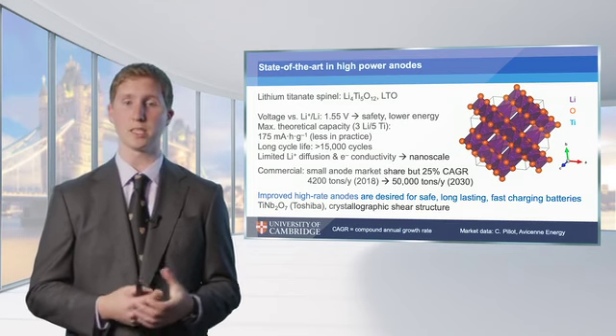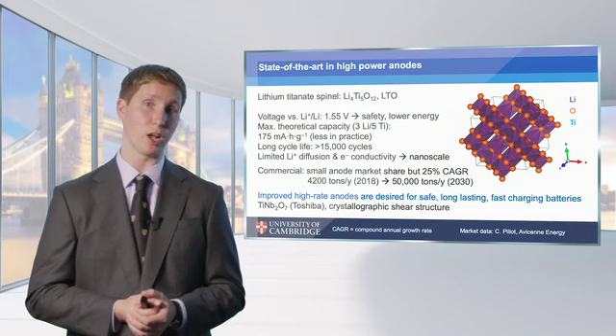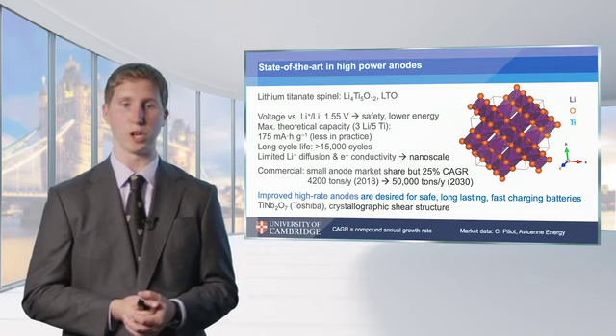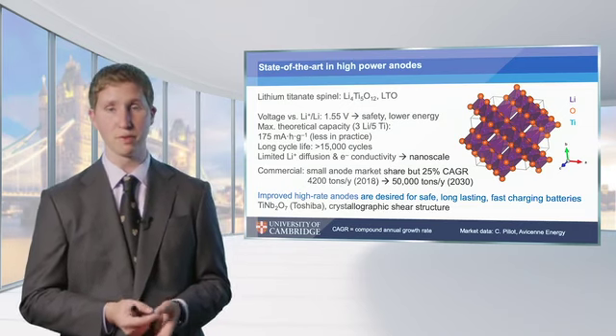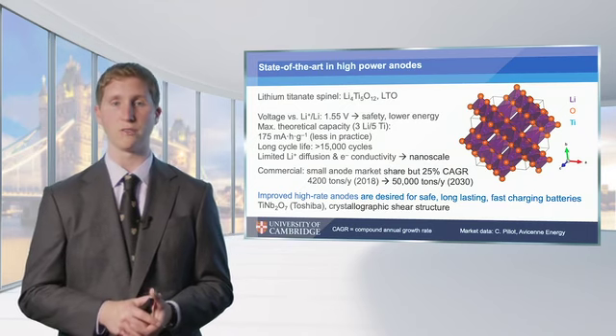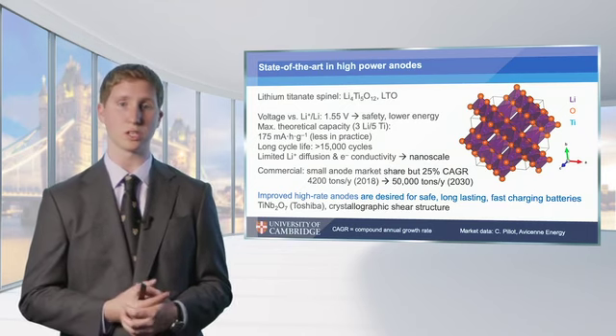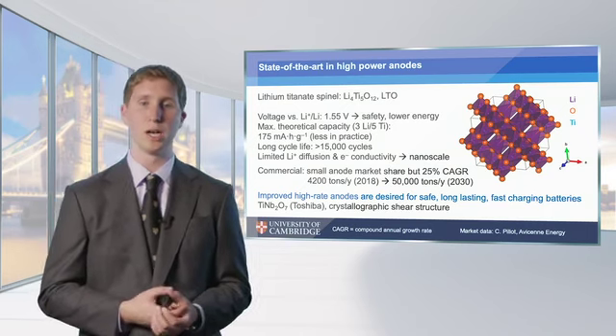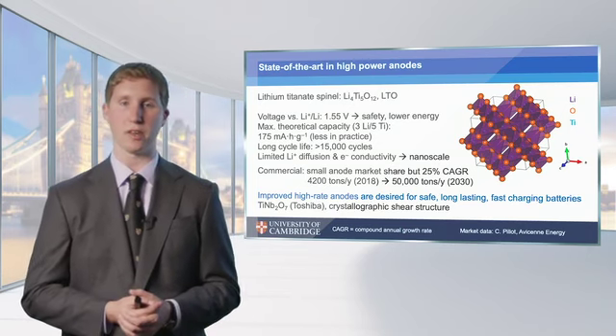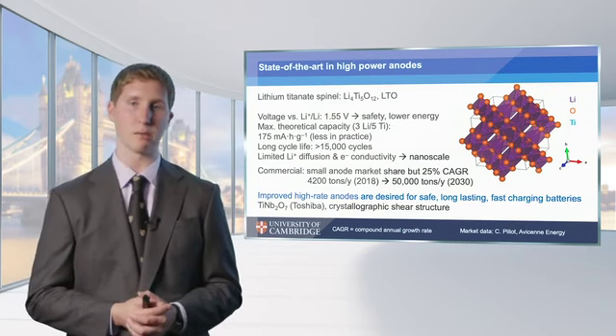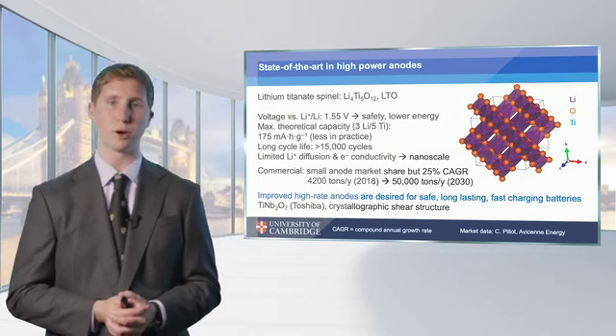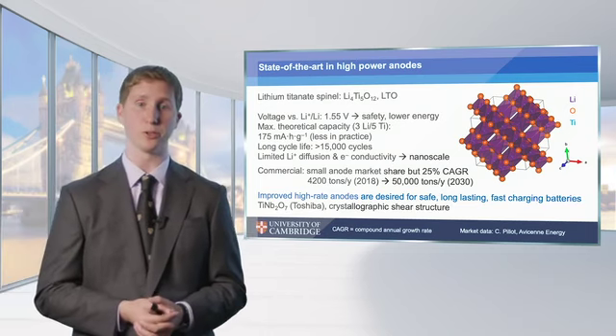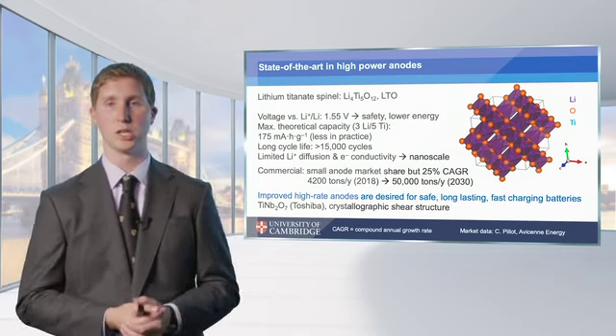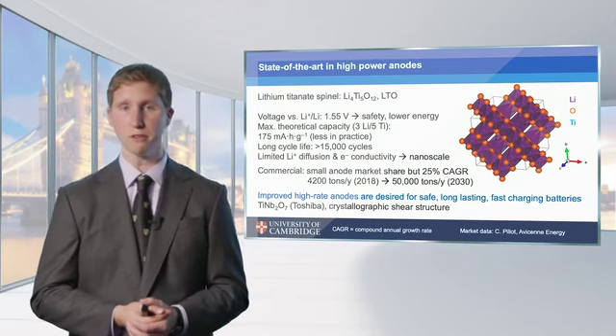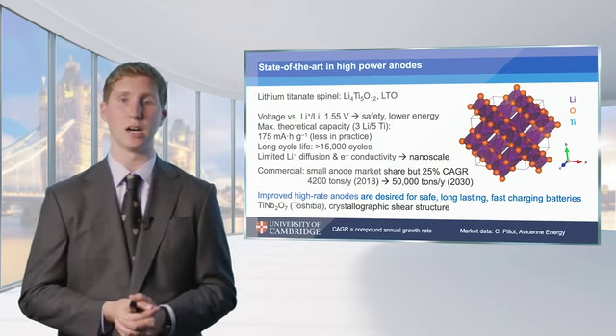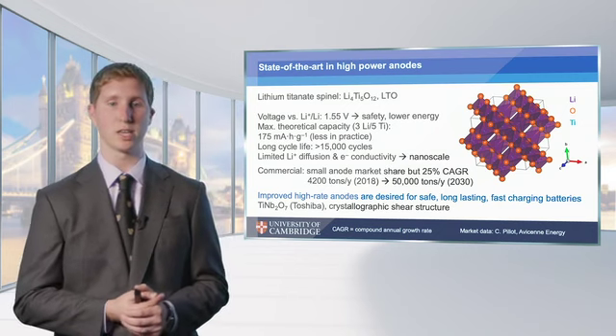But because of this metal oxide crystal structure and because of the voltage it operates at, it's very safe, and it has a long cycle life. Over 15,000 cycles can be achieved with LTO. There is one other caveat: because it has limited lithium and electron transport, the particles do normally need to be nanoscaled to access these high rates, in order to get the particles fully lithiated or delithiated in a sort of minutes time scale.